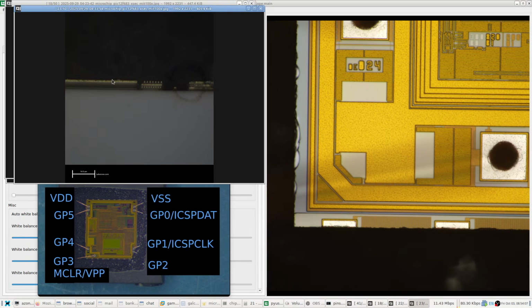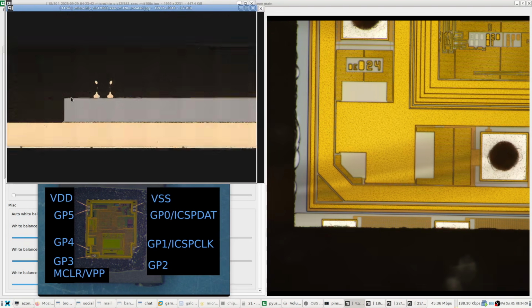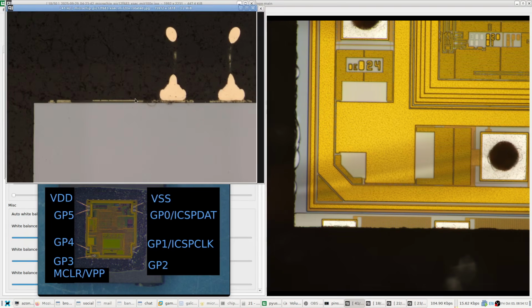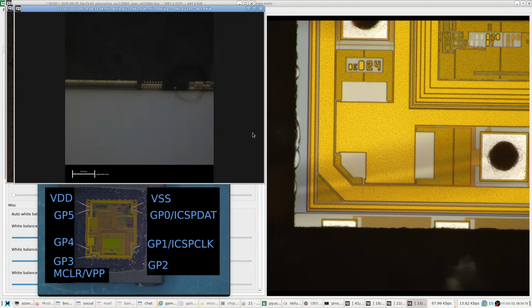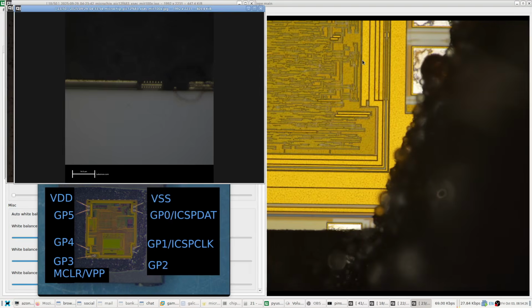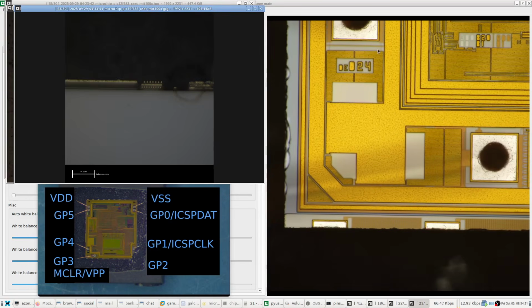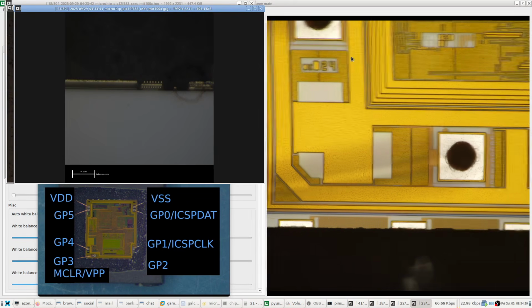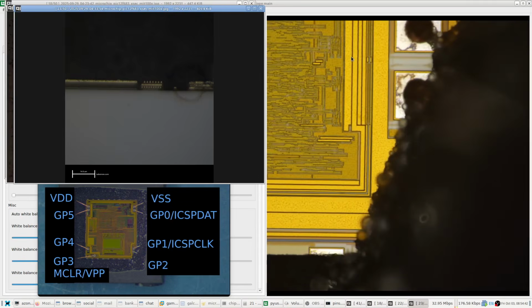And then moving to the right a little bit in the cross-section, so now we're looking at this area around here, just a little bit up closer to the first ball bond, so that's the GP2 ball bond. Again, the actual image is coming from the right side, but that area is partially blocked, so we're looking at the essentially symmetric area on the left. So there's a little bit of dummy fill just below that right-hand bond pad, and so this is probably that area of dummy fill, except this area right here that, again, is mostly covered.